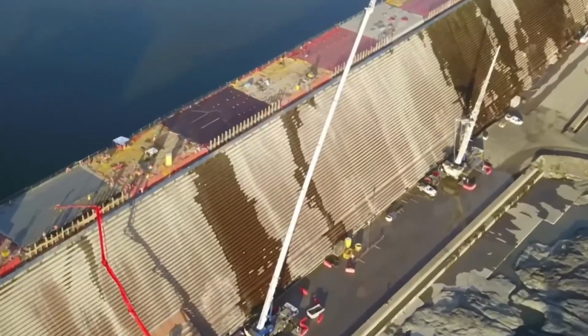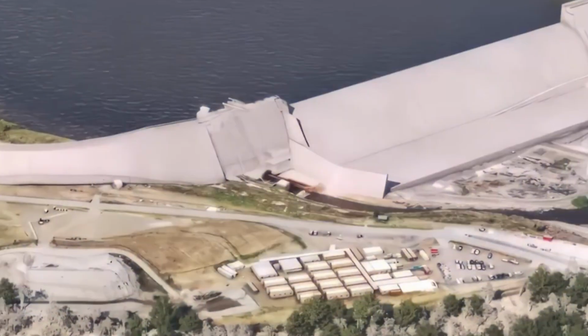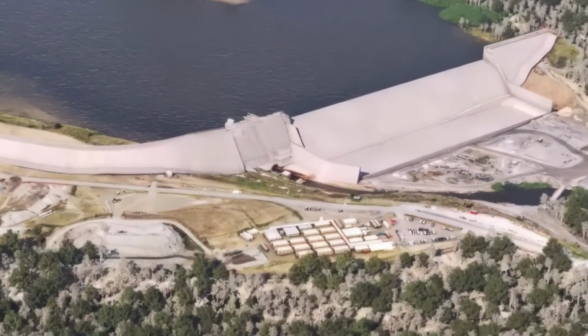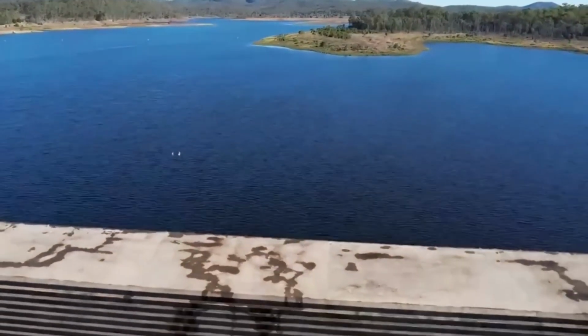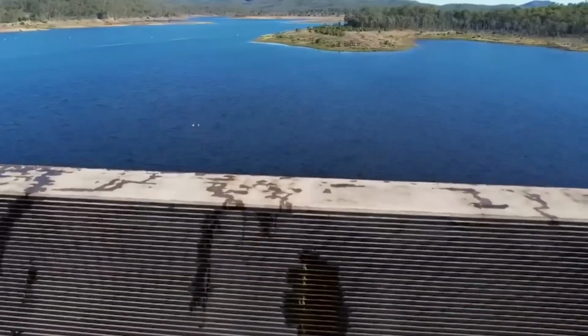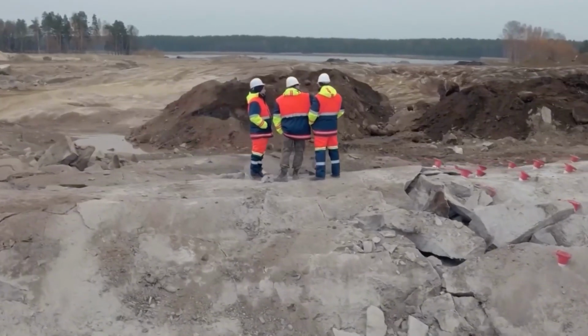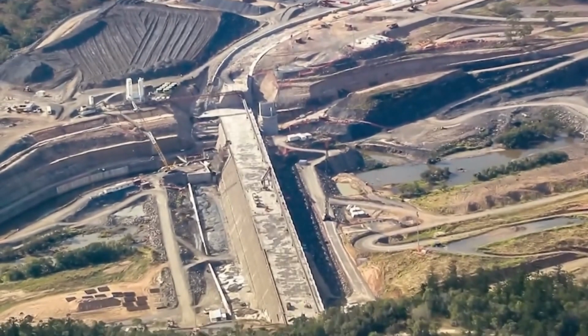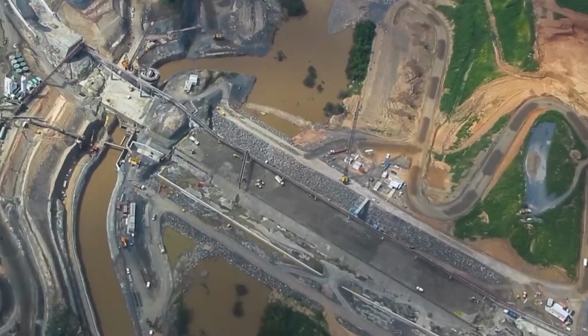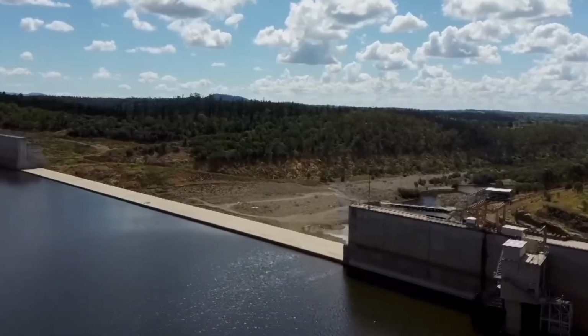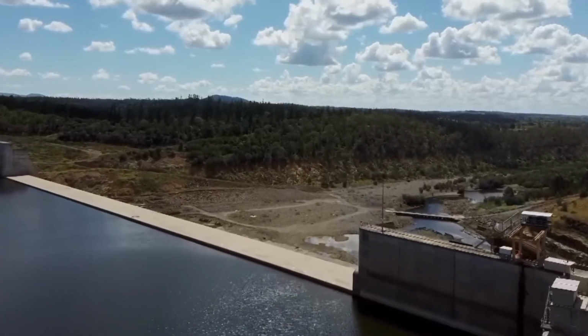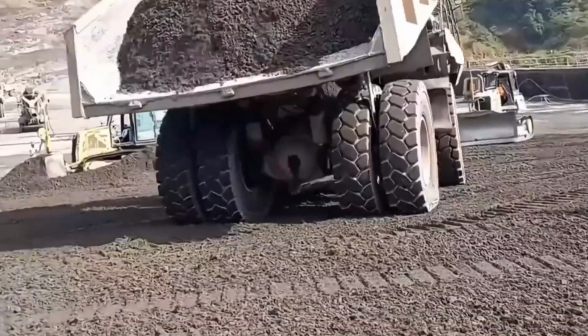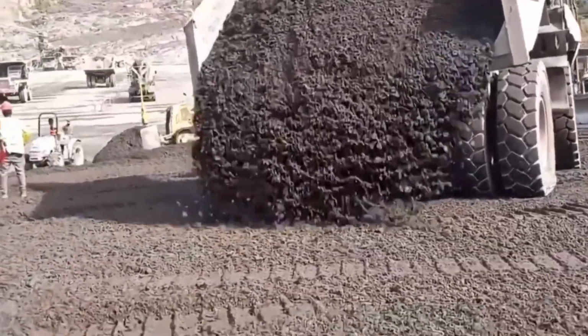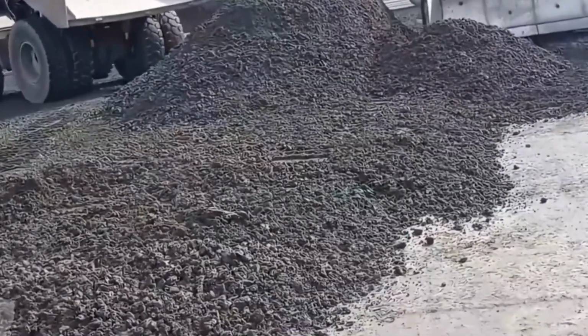Compared to more than 900 roller-compacted concrete dams worldwide, Paradise Dam ended up ranking in roughly the lowest 1% for cement content. A stunning statistic for a structure expected to protect human lives for a century. Third, the roller-compacted concrete lifts did not bond properly. Instead of forming a unified monolithic mass, the layers created weak horizontal joints, essentially built-in fault lines that allowed water to seep through the structure.